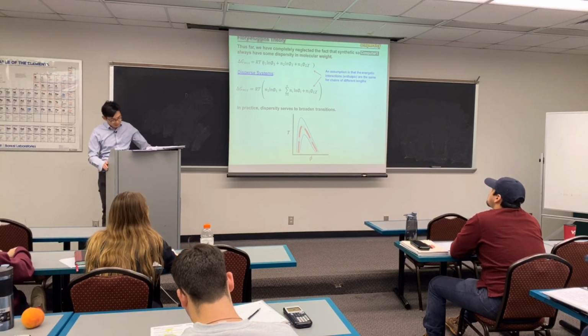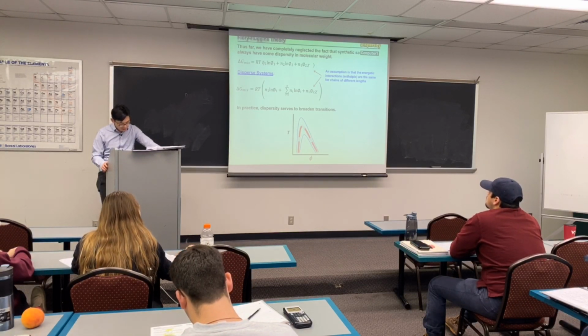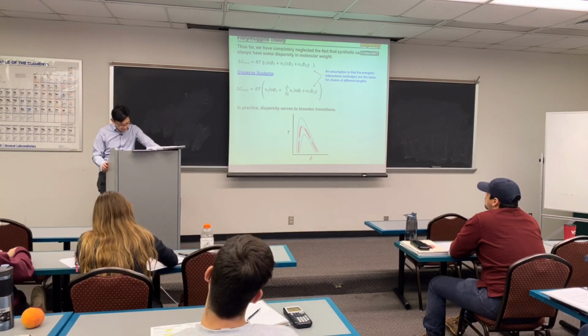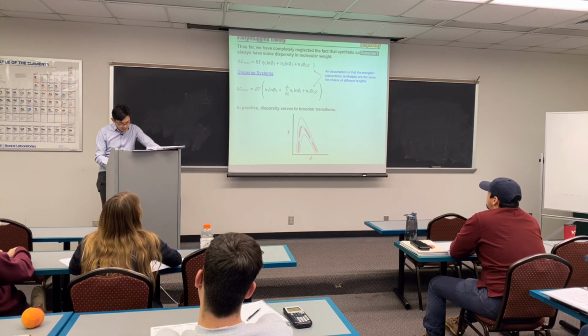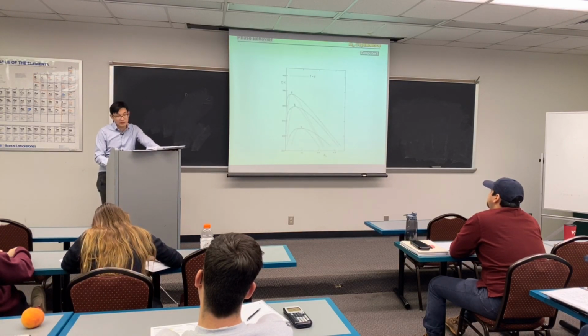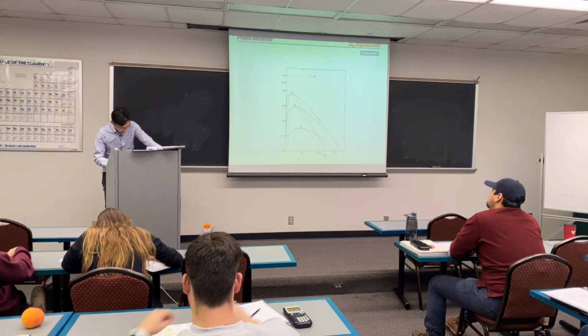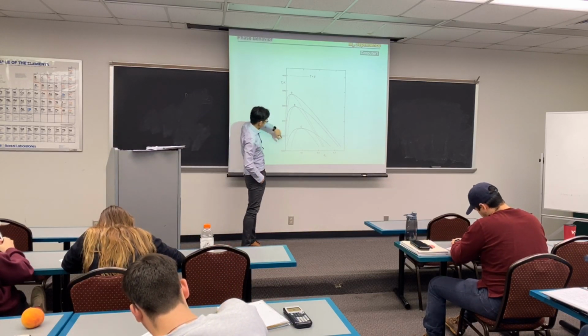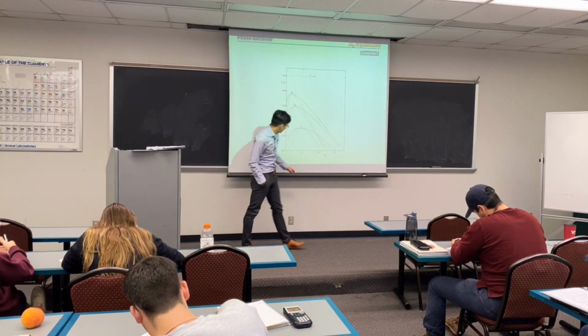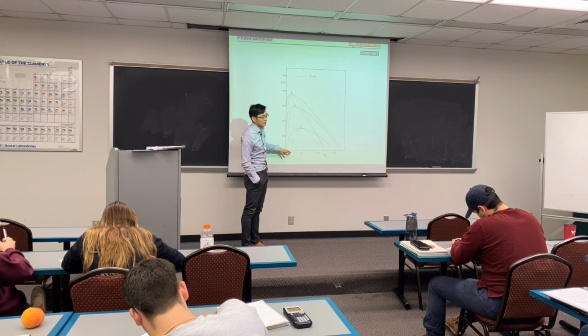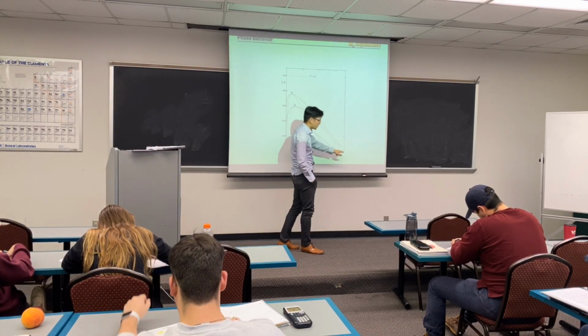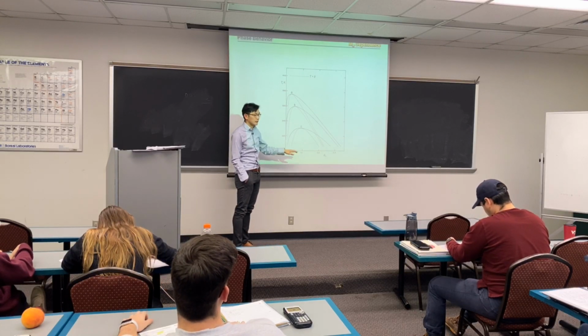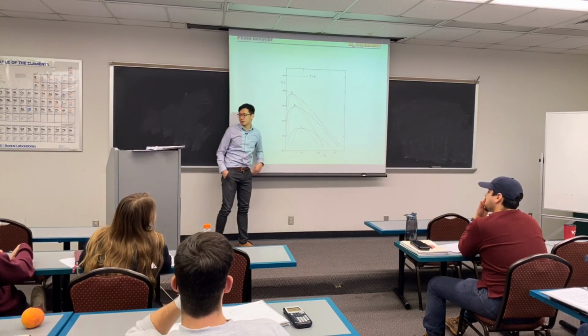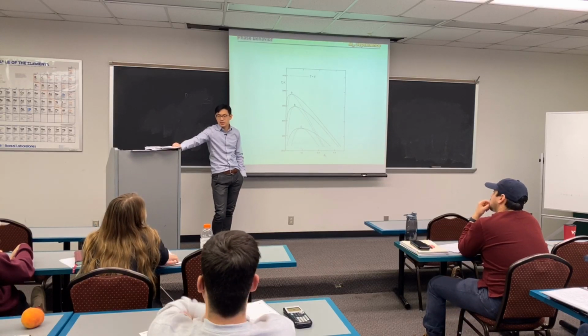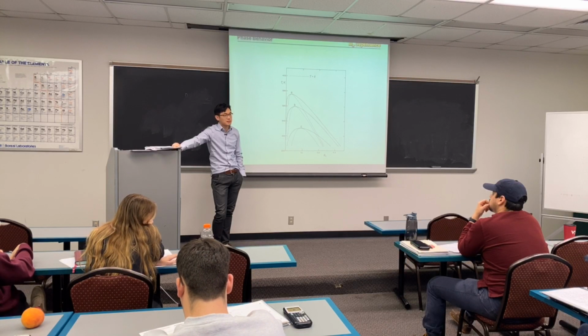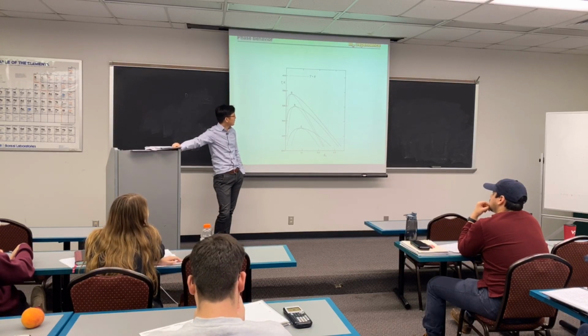So this is the last part where we start to talk about Flory-Huggins theory, where we now apply it when your system actually has polydispersity. So this would be the phase diagram for a polymer in solvent. In this phase diagram, the plot is temperature versus volume fraction. You can see this is only some part of the figure. It's not phi 2 from 0 all the way to 1. This is only a chopped part of it. Because this is a polymer in solvent, that's what you would expect. The phase diagram will be tilted towards one side versus the other. Okay? It's not going to be symmetric.